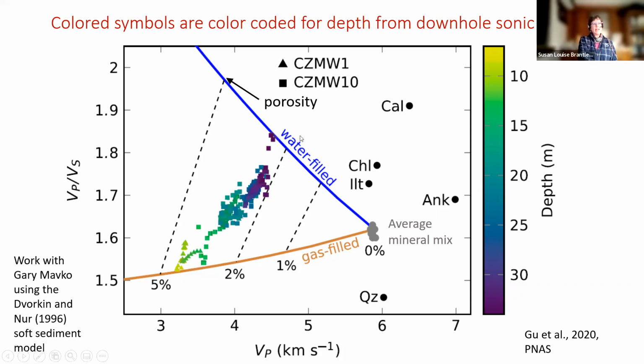And then as they shallow in this borehole, they stay roughly constant in porosity for a while, and they move towards a gas. The only way we could explain the data is by a gas-filled model. So we discovered from this that even below the water table, there actually is a fair amount of gas in the shale, much deeper below the water table. And it's the only way that we can explain the data.